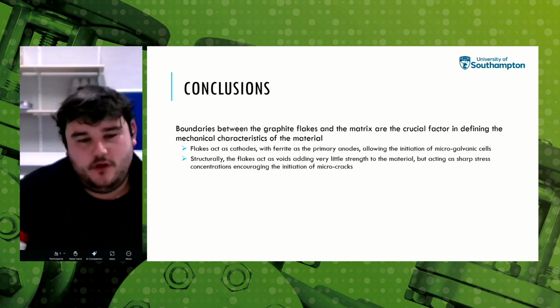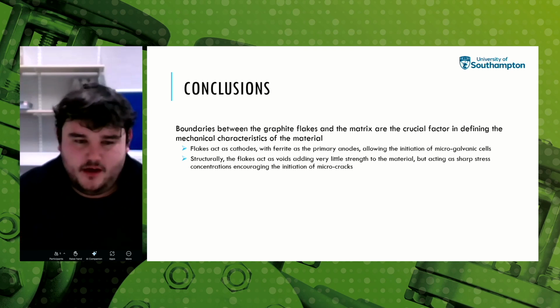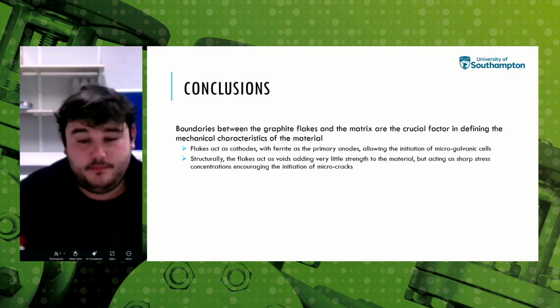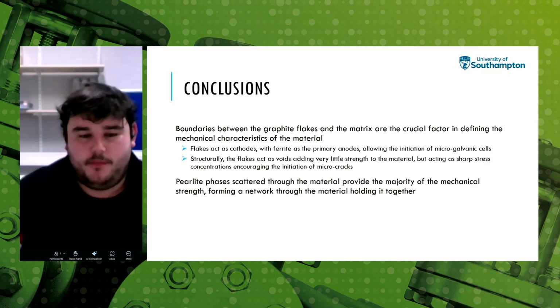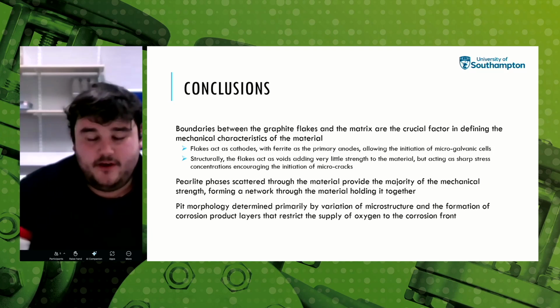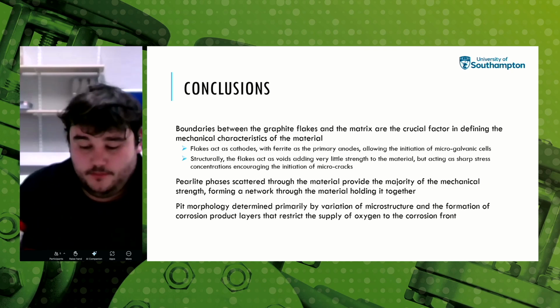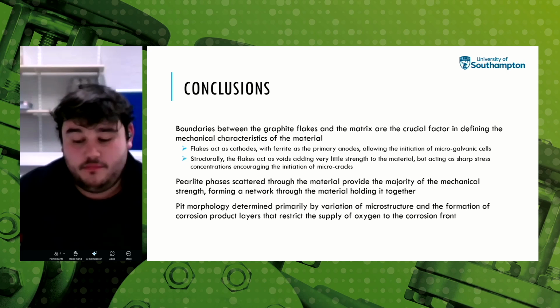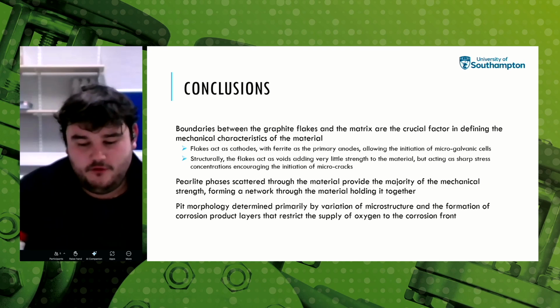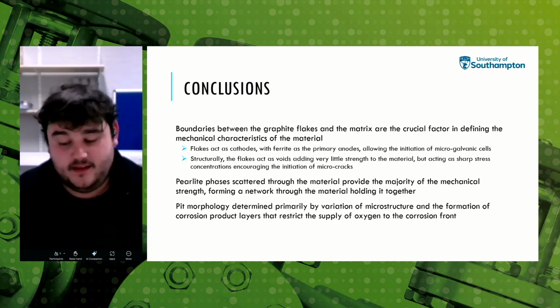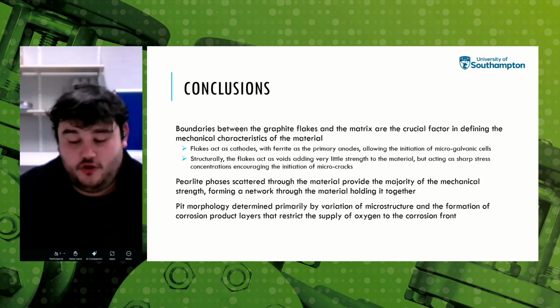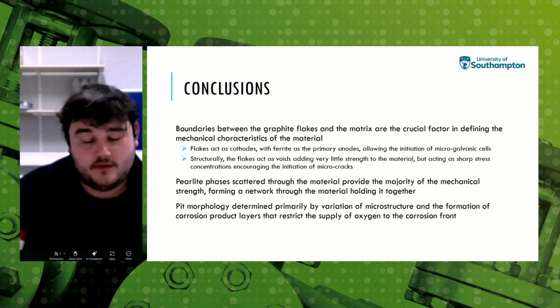From a corrosion point of view, we have these microgalvanic cells with graphite flakes acting as cathodes and ferrite acting as anodes, that begin to propagate indefinitely, with nothing to restrict the reaction except that corrosion product layer that restricts the oxygen supply. We will see that pearlite provides the mechanical strength of the material, forming an intertwined network that holds the material together, with the ferrite graphite regions filling in the gaps. And it's this microstructural variation that drives where these initial pits will be formed, and therefore the likely regions where there will be initiations of pinhole leaks.